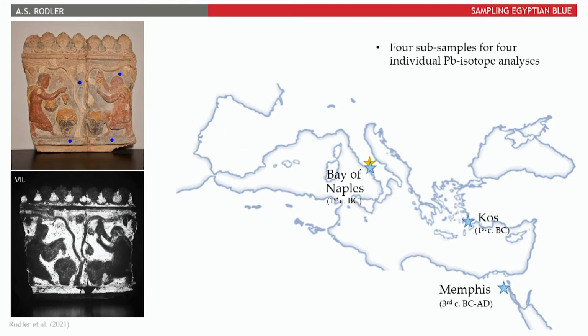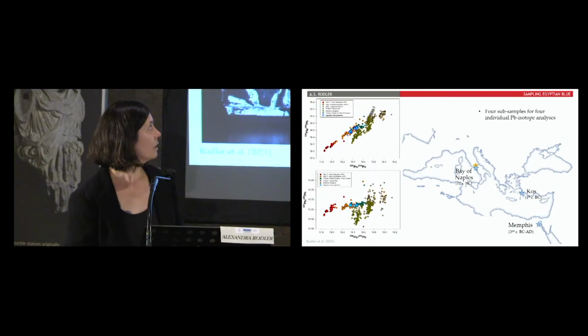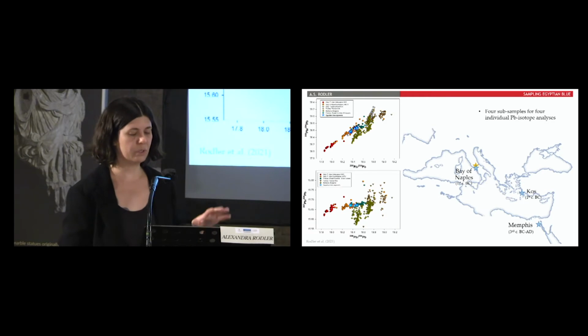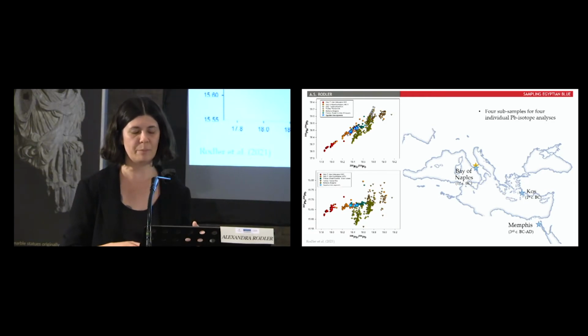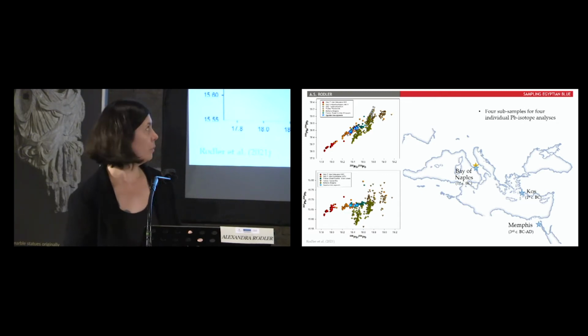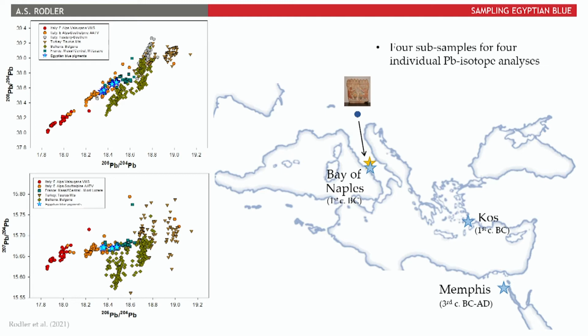But I wanted to have a look at this again to see if we could refine the provenance evaluation a bit better. So I asked my bachelor thesis student at the Vrije Universiteit Brussel to just treat 4 samples as individual samples and analyze them as individual lead isotope samples. And the results, you can see here, so the plot a little bit better, so we can see the alignment of the samples better and also how they match with the reference data. So this increased sample quantity allowed us then to propose that copper from the Eastern Alps was likely used instead of the Iberian. That was a bit of a mixed signature where we weren't quite sure if it's really correct.